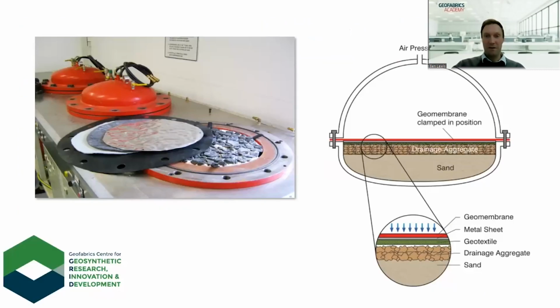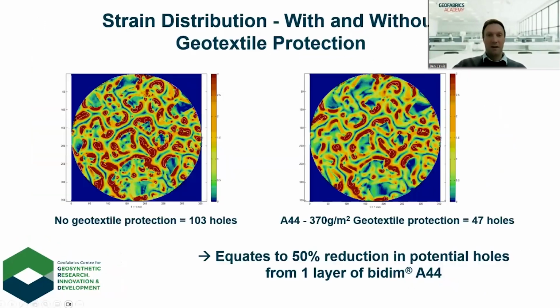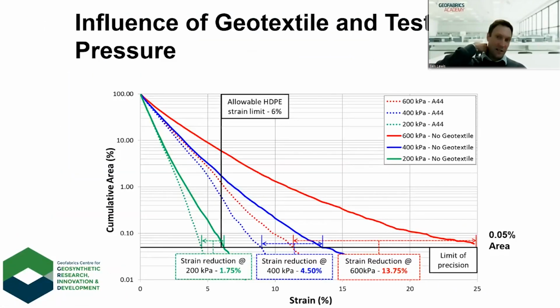So we do that test in the lab, and it's essentially what they do, by the way, is they take out this thin film which has been loaded up. There's a little thin sheet in there between the membrane and the geotextile, and they run it through a strain distribution profile. And what this chart here essentially shows you, and this is the extreme case, obviously, but you get 103 holes with no protection and 47 holes with protection. So it's a massive reduction with geotextiles. But what we try to do is really hone what geotextile is going to be most appropriate for your rock or maybe a rocky subgrade.